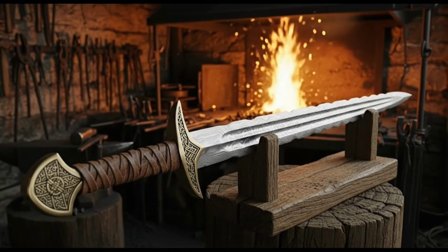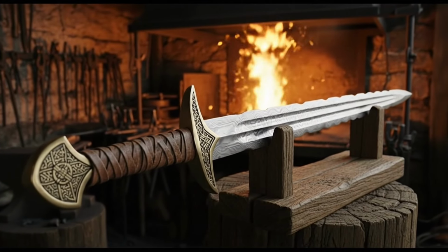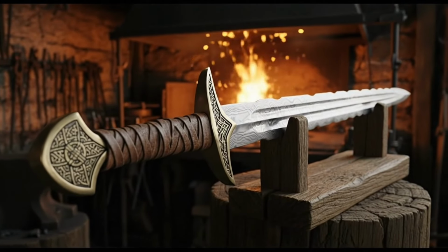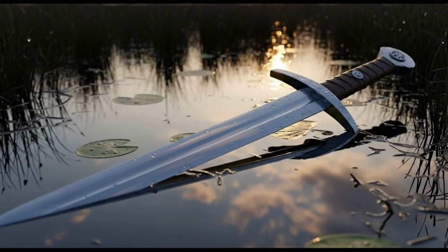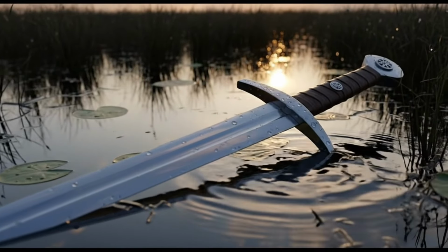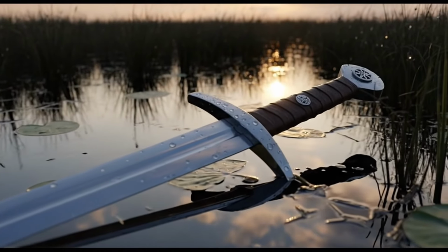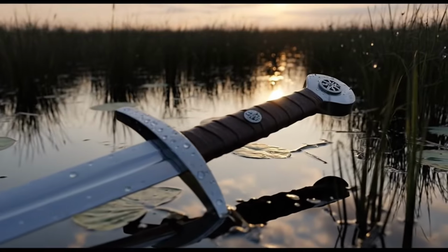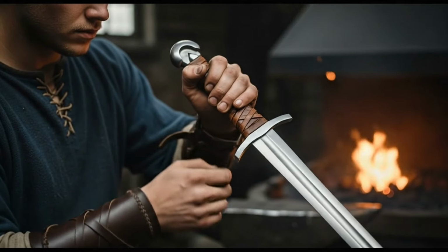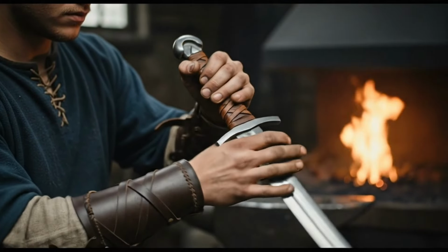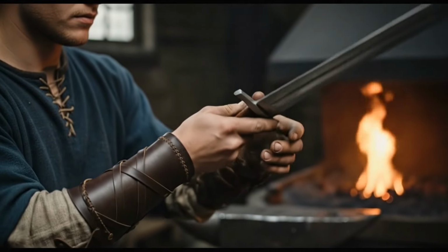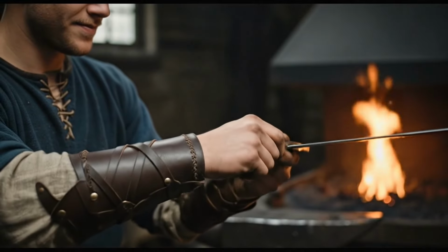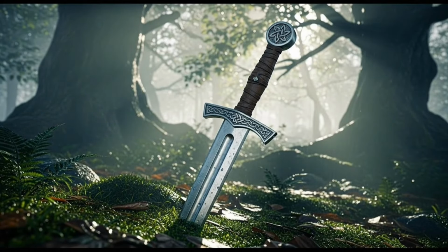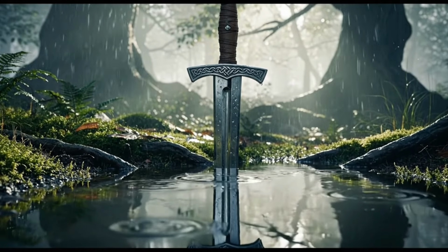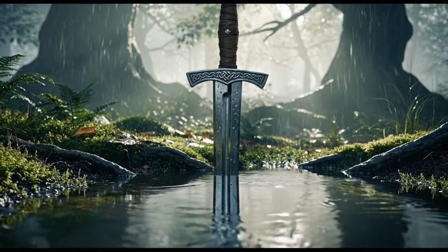Then red-hot blades had to be cooled very quickly. They were immersed in large containers of water, oil, or even snow. Sudden cooling changed internal crystal structure of steel, making it extremely hard, but also very brittle. This moment was pure magic and lottery. If blades were heated unevenly or had internal defects, they could crack or warp right in the middle of hardening procedures. Historians believe the percentage of rejects at this stage was very high, even for experienced craftsmen.